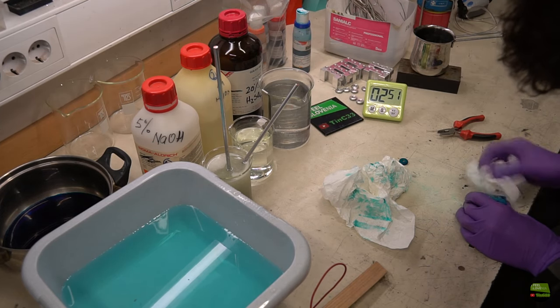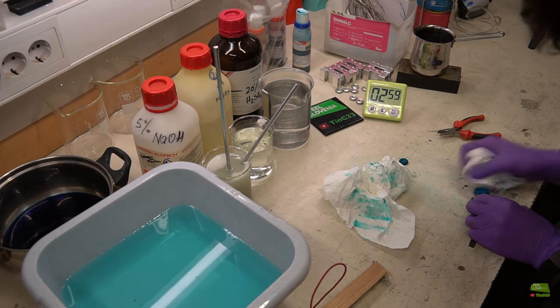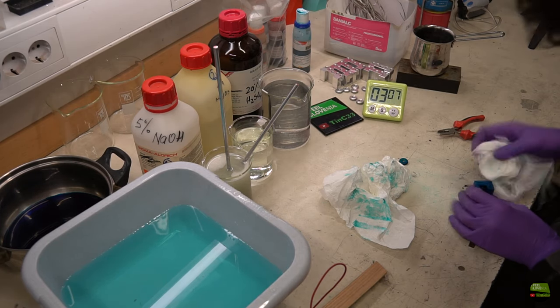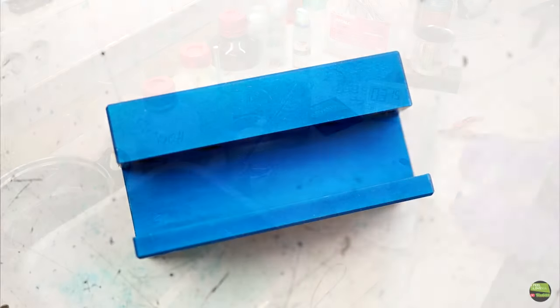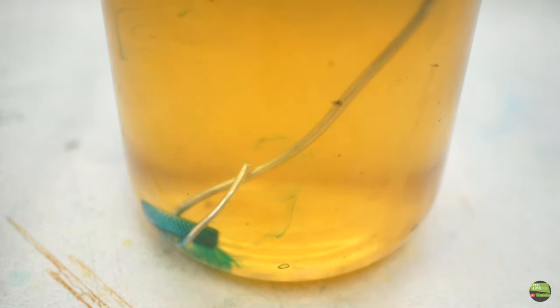After that, rinse and cool the part with water and then wipe excess color with a towel. You can also slightly polish if you want a more shiny part. If something went wrong, just return to step one and sodium hydroxide will remove any anodizing, also industrial ones. But the solution will become dirty. So I have a special container of sodium hydroxide for removing old anodizing.